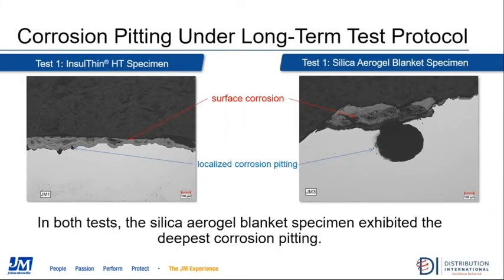Now, when I present this data to corrosion engineers, they take a look at the pictures. They usually say, hey, that's great. But then when I show them this, this is really what they're interested in. So what we're seeing here is a close-up picture of the pipes, and it's basically a cross-section. So I'll explain what's happening. The graphic to the left there, test 1 Insulthin HT sample. The black part at the top is actually just background noise. Then we can see the surface of the pipe. The red line indicates where the surface corrosion is. The white part at the bottom is the actual pipe itself. And then those little black areas where the blue line is pointing, those are the pits, that highly localized form of corrosion extending into the pipe itself.